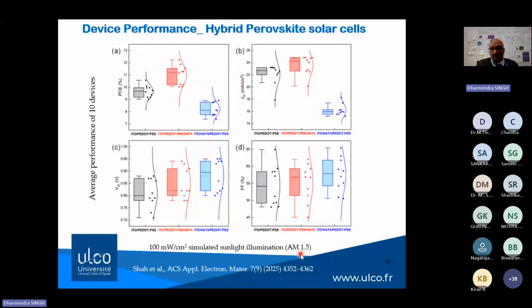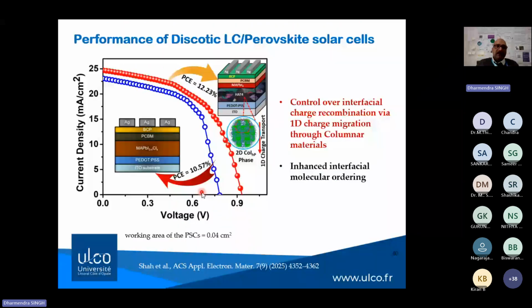We fabricated 10 devices and investigated all parameters like PCE, JSC, VOC, fill factor, and so on. And here is the conclusion. The parent device without any columnar interfacial layer had a PCE of around 10.5%, and when we introduced this columnar material at the interface, the PCE increased to 12.2%. So we can say that control over interfacial charge recombination via one-dimensional charge migration through columnar material is responsible for this increased PCE. The presence of one-dimensional molecules, with charge transportation restricted to one dimension, improved the molecular ordering at the interface.